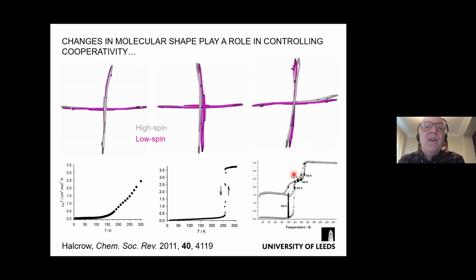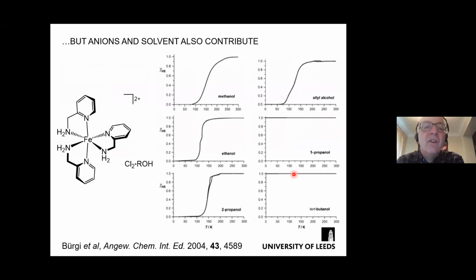However, if your complex is a salt, if it's a cation, for example, then this will not be the only thing in the crystal. You will have anions in the crystal as well. Perhaps you will have lattice solvent. And these inert parts of the crystal also play a role in its function. Now, a classic example of this was published by Professor Bürgi in Switzerland, I don't know, 17 years ago now, where he looked at just 6 alcohol solvates of this simple complex salt. And he found that the 6 solvates showed very different spin state properties.